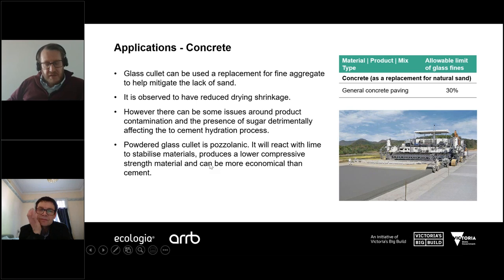One of the advantages to using recycled crushed glass in concrete has been the observed reduction in drying shrinkage. So the incorporation of recycled crushed glass has been shown to reduce the drying shrinkage, which is particularly advantageous for the use of concrete.